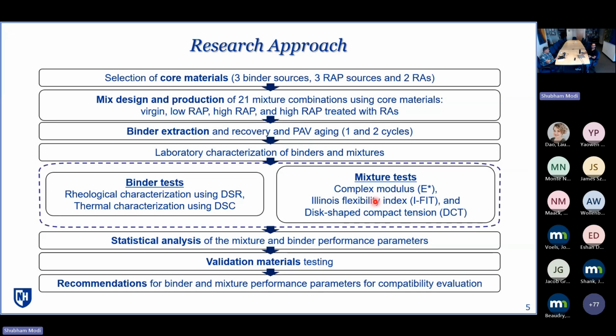The difference between low RAP and high RAP mixtures is just the percentage of RAP incorporated into them. Low RAP mixtures include 25% RAP content, whereas high RAP mixtures contain 45% RAP. This was followed by binder extraction and recovery and PAV aging on those blends.